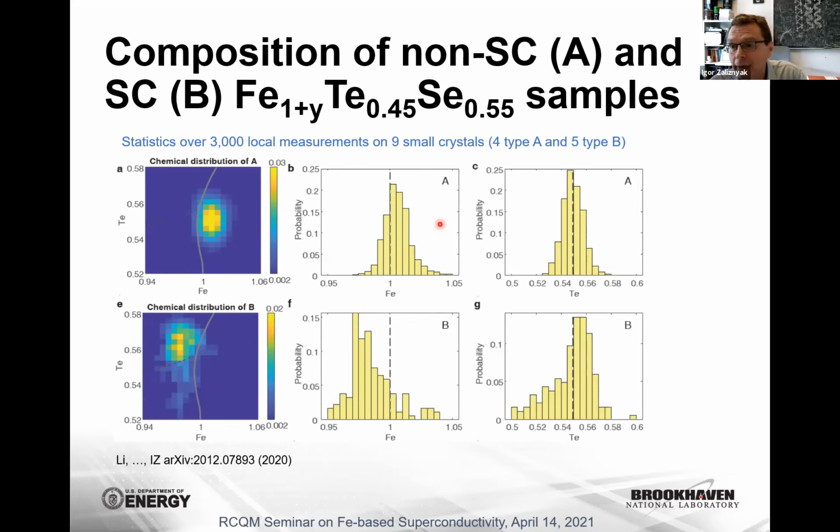As I've just said, the amount of extra iron is so small. We have measured the full volume with unpolarized as well as polarized neutrons. So diffuse scattering is totally dominated by magnetic scattering. There is no structural diffuse scattering that can be seen to be associated with structural disorder and imperfections.